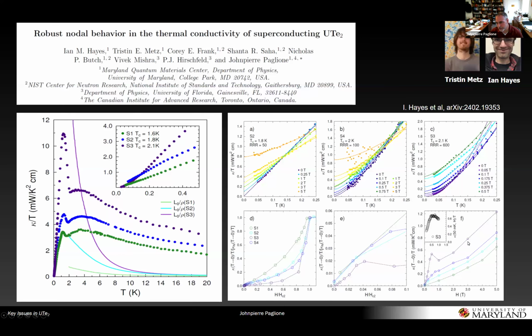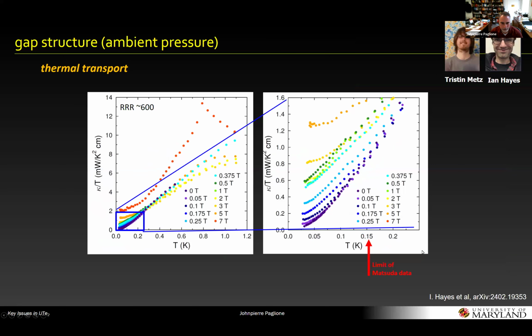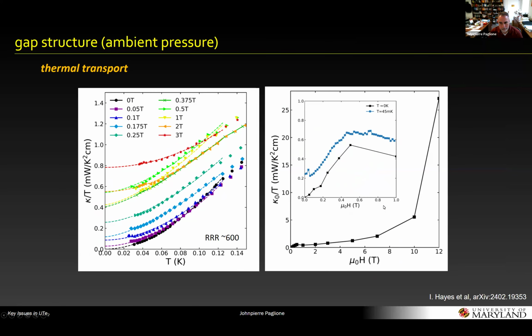Okay, there are more interesting things, and I won't go into that, but for instance, if you look at the intermediate field regime, there's actually an interesting peak here. I think I show it. Yeah, I show it here. Just to show that for this highest TC sample, if you put a large error bar, of course you can call this a 0, but in fact it's not. There's a rapid rise, and this is consistent with the so-called Volovik effect, to do with the shift in the energy spectrum for nodal excitations.